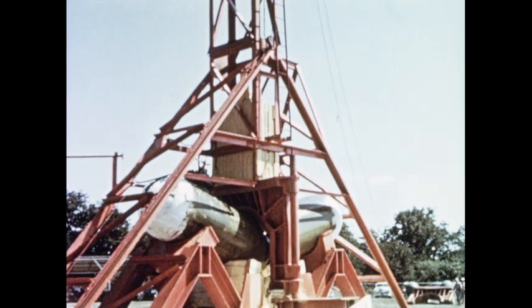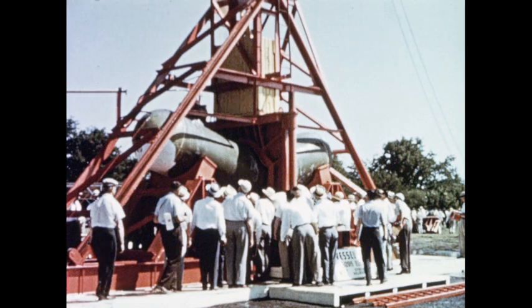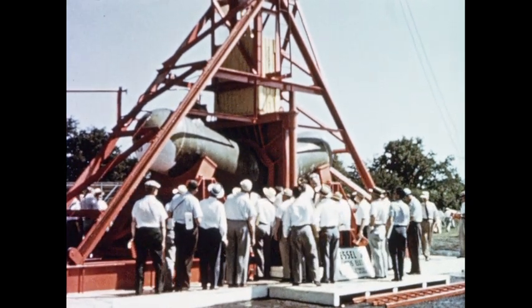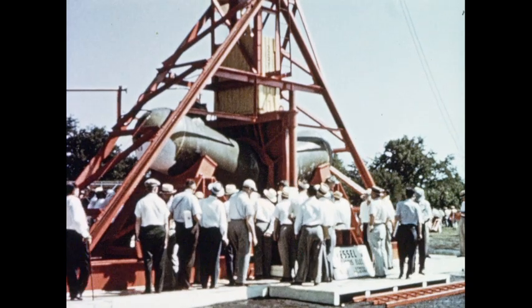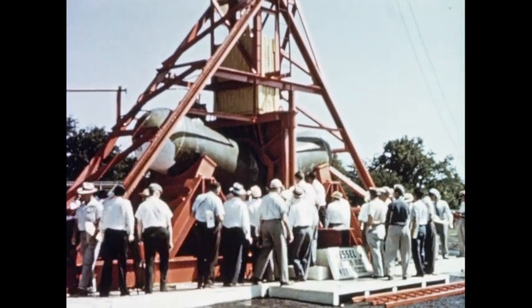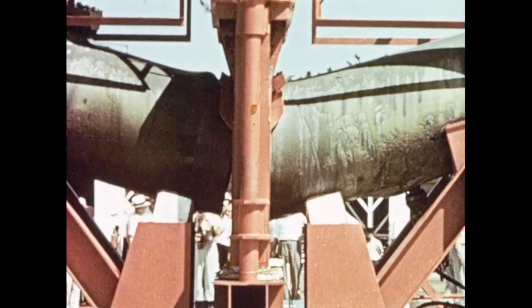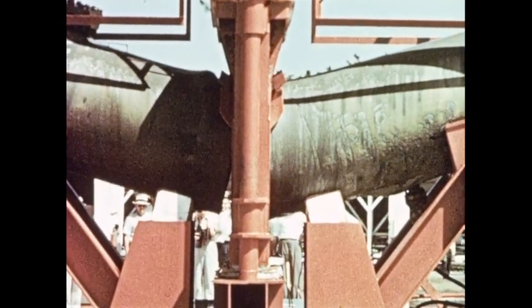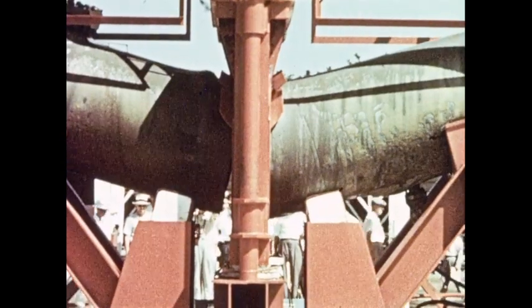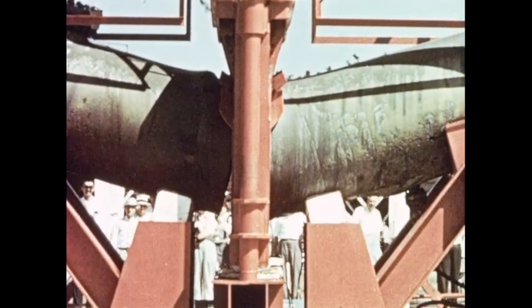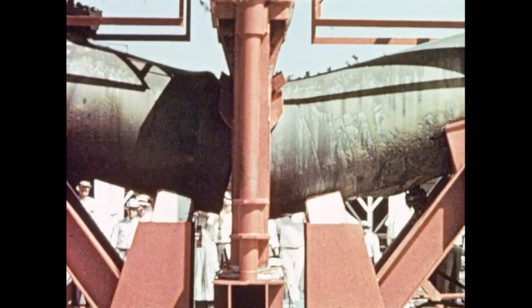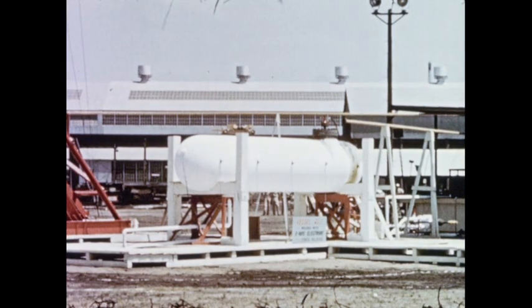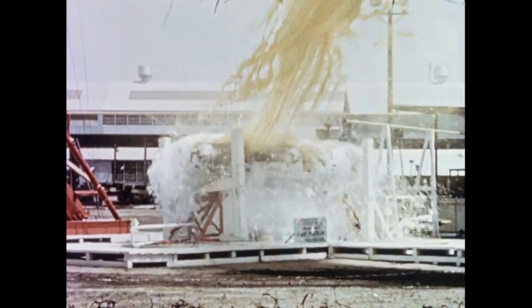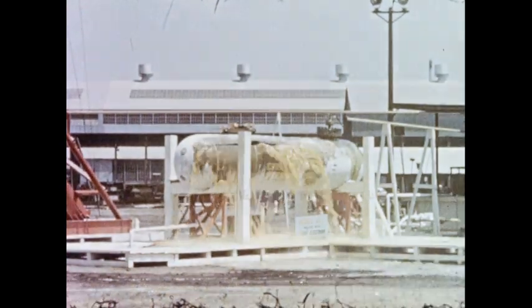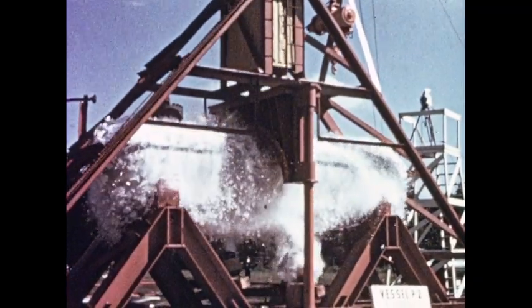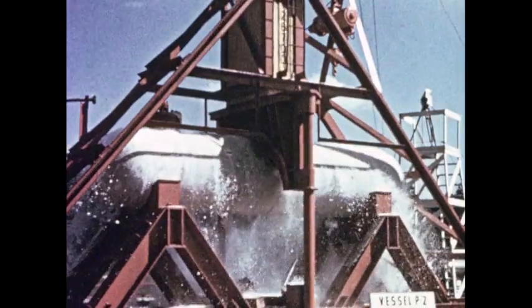There was no question that T1 had remarkable mechanical properties. And again, the experts were surprised by the kind of rupture, an absolutely clean tear, despite the terrific impact. Here was conclusive evidence of T1's unique properties, a combination of ductility and toughness not usually expected in the same steel. A second series of tests confirmed the dramatic performance of T1 steel. The results were almost identical. Again and again, the unique combination of toughness and strength was conclusively demonstrated.